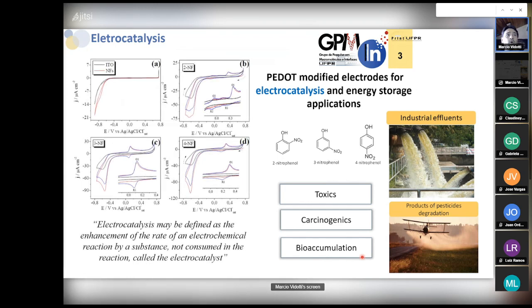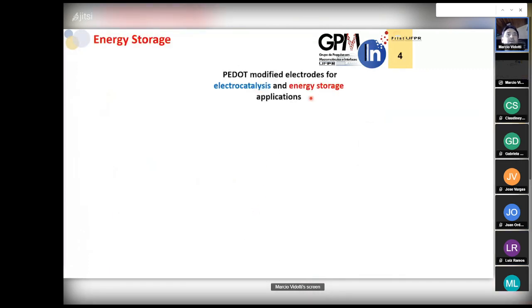And a few years ago, we developed a kind of modified electrode. Here I'm showing some results. I'm not going to go into details about the electrochemical response, but using this modified electrode, we can see clearly the response of the 2, 3, and 4 nitrophenol towards the reduction and oxidation at this modified electrode using PEDOT. Clearly here, we cannot find any electrochemical response for those molecules, but using PEDOT, the electrocatalysis was promptly observed.